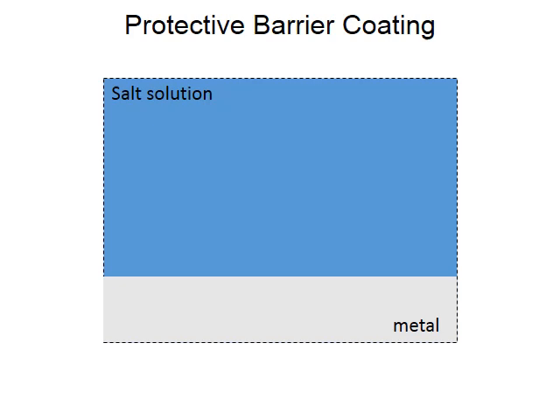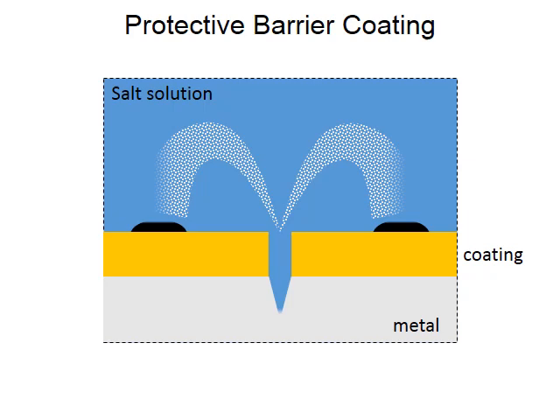To quickly recapitulate what happened in our experiment: the metal surface was coated with a polymer film, and this film was mechanically damaged by scratching. As a result, the metal surface is now exposed to the electrolyte solution, causing it to corrode. When this process continues for a long time, it will lead to the growth of the scratch by corrosion. This can lead to a detachment of the protective coating around the scratch — a process called delamination.